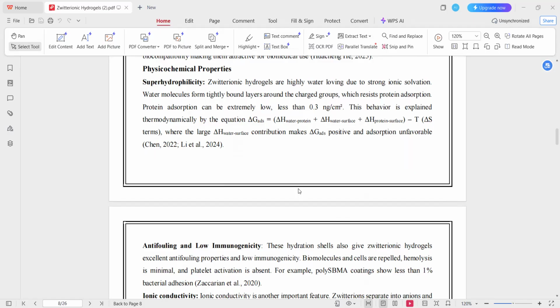So first of all, we are going to explore its superhydrophilicity and surface hydration. The most fundamental property of zwitterionic hydrogel is that they are super hydrophilic. This means that they have an exceptionally strong affinity for water. The positive and negative charges present in each zwitterionic unit attract water molecules through ion dipole interactions. As a result, water molecules form a tightly bound and highly ordered hydration layer around the polymer chains. These hydration layers are much more stable than hydrogen bonding water layers found in neutral gels, such as PEG, polyethylene glycol based hydrogels. Because the water molecules are strongly bound, they are not easily displaced. This leads to extremely low levels of protein adsorption, often below 0.3 nanograms per square centimeter, which is considered near zero fouling.